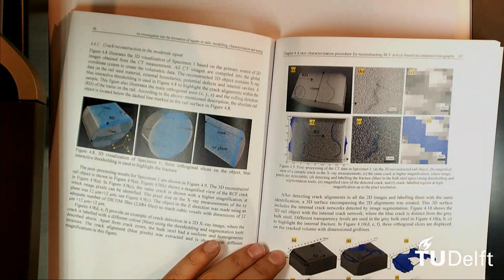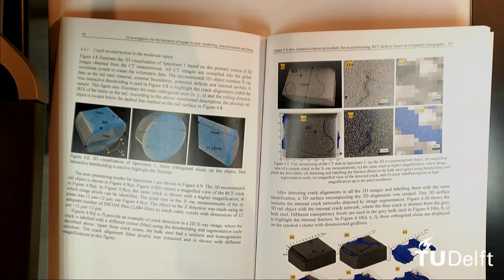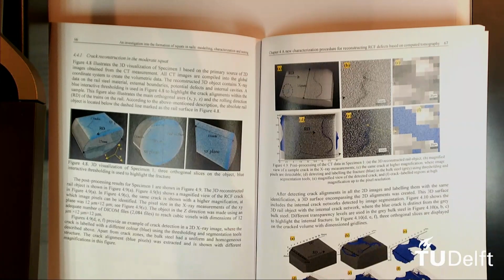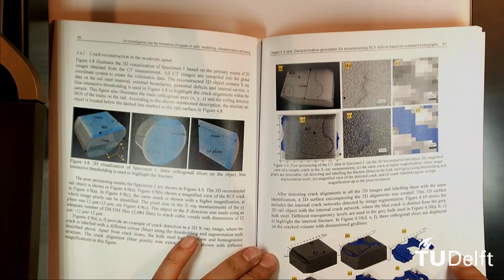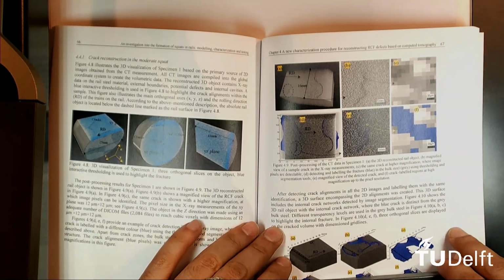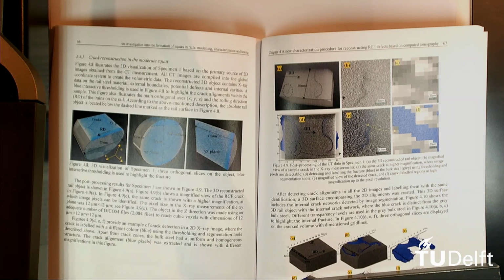And yes, the top right figure C is the direct observation, I guess, where the grayscale is the intensity. And then you move to figure F, in which you see the crack has become blue. So going from C to F, you have some criterion what to call a crack or what not to call a crack. You don't give any quantitative information on that.